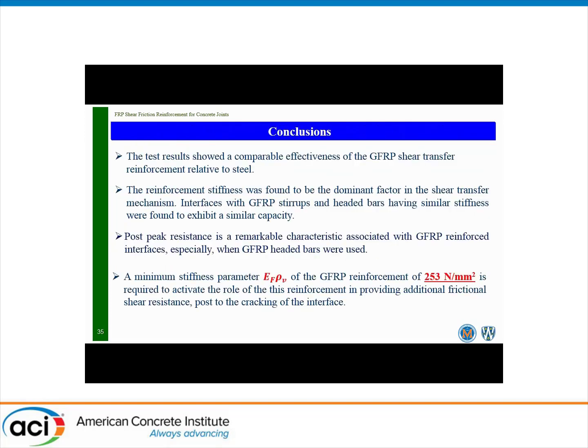In a nutshell, we can draw a few conclusions. Test results showed that GFRP reinforced interfaces as shear friction showed comparable effectiveness to steel reinforced ones. The reinforcement stiffness was found to be the dominant factor, mainly due to the perfect linear characteristic of GFRPs, as opposed to the yielding of steel reinforcement. The minimum recommended reinforcement content to ensure we still have some strength and sustain the load after failure should not be less than 253 megapascal.